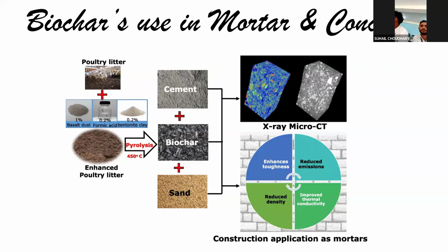When you produce cement, you emit lots of greenhouse gases. Now, if you can find some material that can be used as a replacement for cement, that is a win-win scenario for you, right? So what we did, we used poultry litter. This is chicken litter, and we used basalt dust, formic acid, and bentonite clay to enhance this poultry litter, and then we pyrolyzed it, and we got the biochar. Now this biochar is produced from poultry litter, and we use cement, sand, and of course you need water, and you get the concrete.